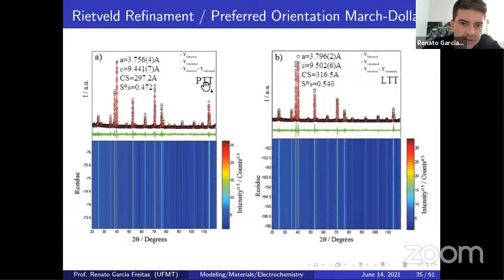So we obtained the previous thermal treatment, later thermal treatment, Rietveld refinement again, and observed the a parameter, c parameter, lattice parameters, isn't it? And a preferred crystal orientation on the c-axis. As we observe here, if you know crystallography, you know that it's preferred oriented, because we don't have the small decreasing like a sine function as in this part. So we used, I cannot read it here, probably the March-Dollase approach, to obtain the preferred orientation. And the crystal size is 297 previously, later 316.5, and the lattice strain 0.4, 0.5, from the refinement.